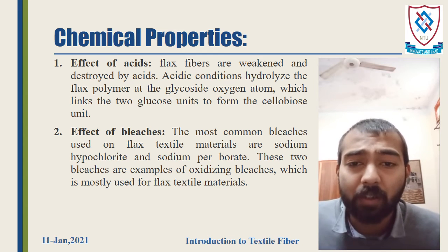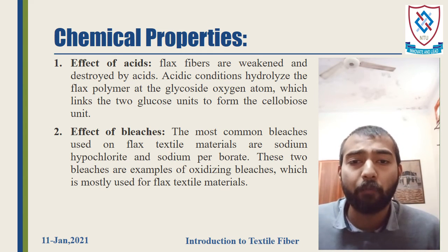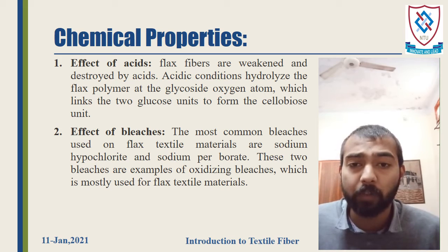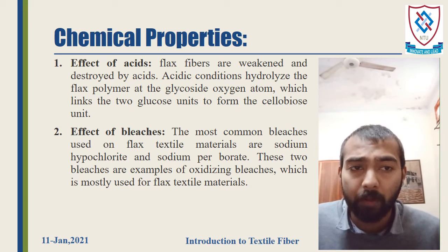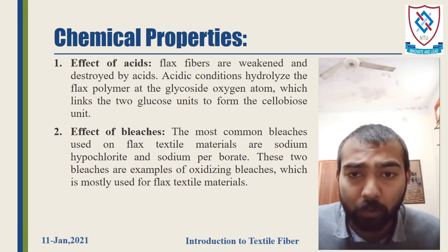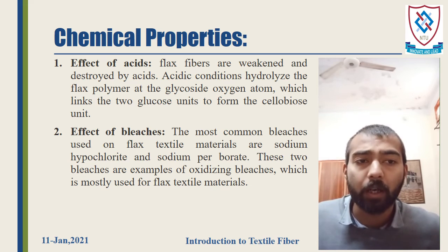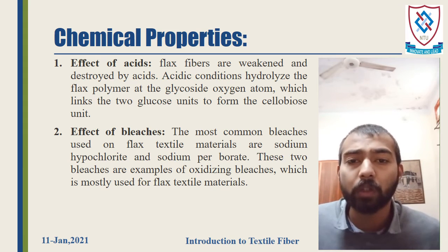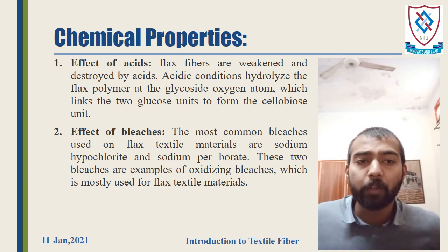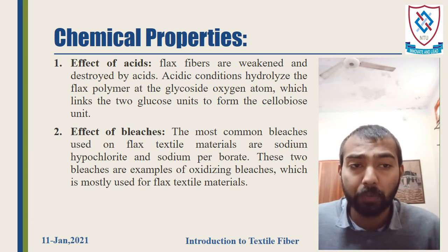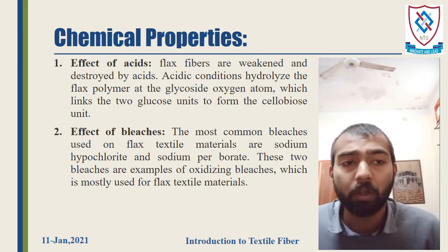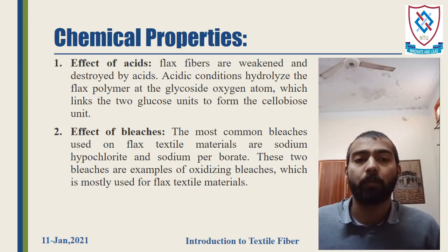Now we will discuss the chemical properties of flax fiber. Effects of acid. This is the first one. Flax fibers are weakened and destroyed by acid. Acidic conditions hydrolyze the flax polymer at the glycoside oxygen atom, which links the two glucose units to form the cellobiose unit.